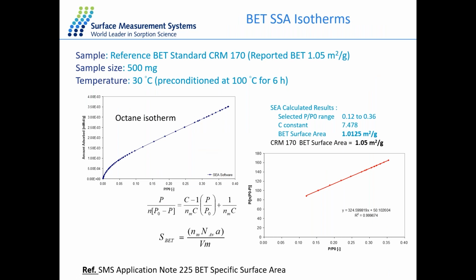This is an example of one of our BET experiments. In this case, we're using a standard aluminium sample. We are carrying out the experiment at 500 milligrams of sample, 30 degrees Celsius, and we've preconditioned our sample at 100 degrees for 6 hours. With the IGC-SEA system, we have in situ preconditioning. What this does is precondition our sample before any of our experiments, at a higher temperature if necessary and for longer periods of time, before we start our experiment.